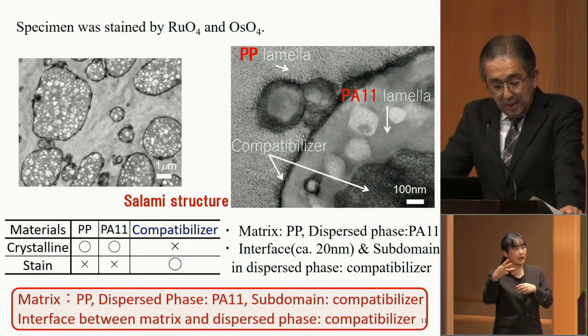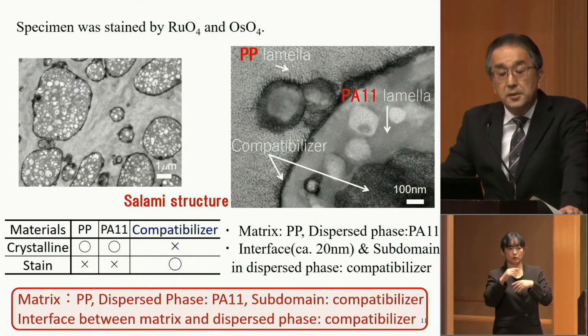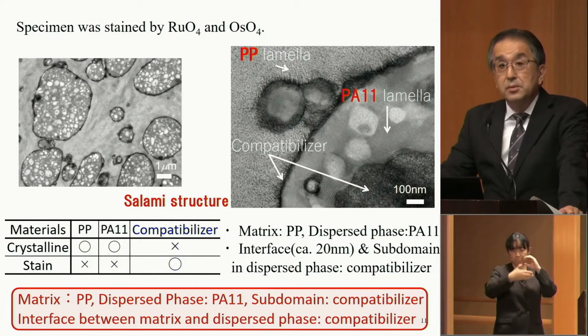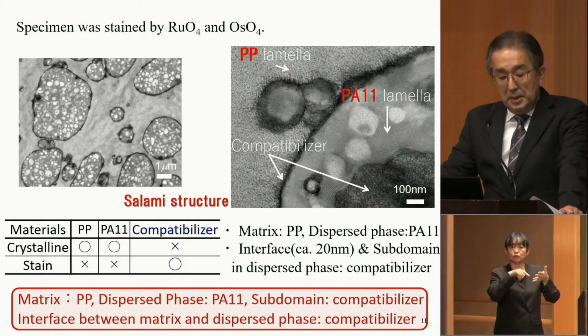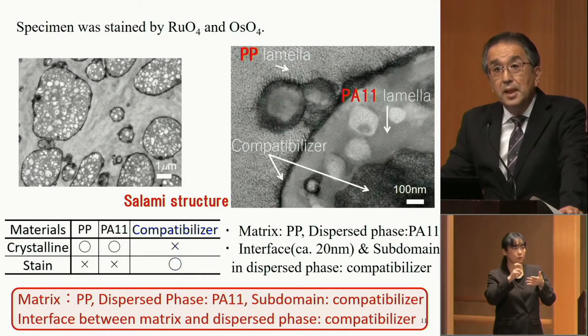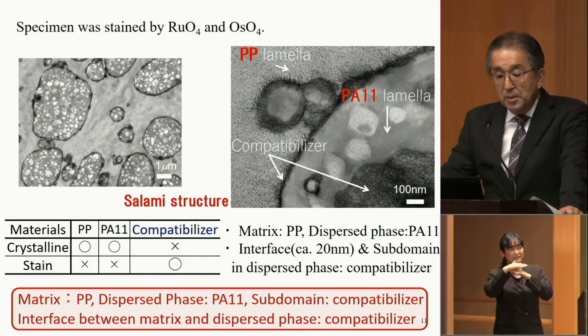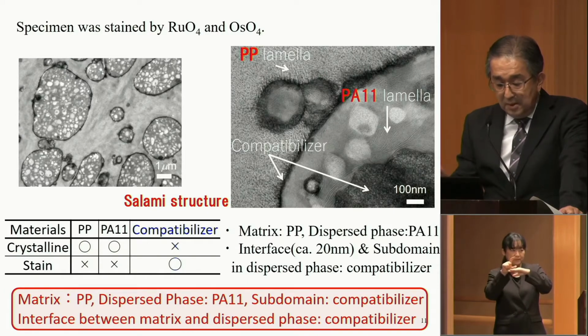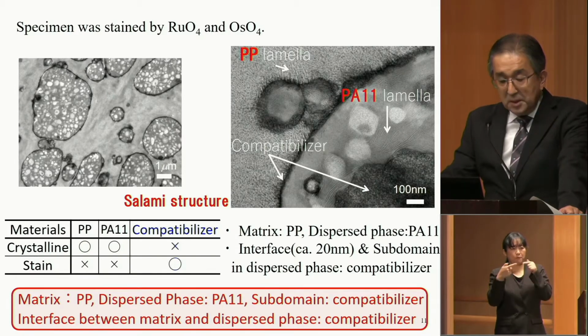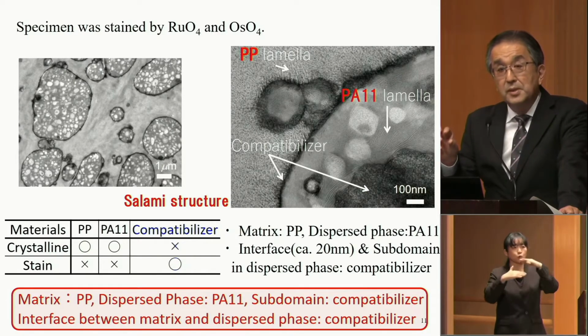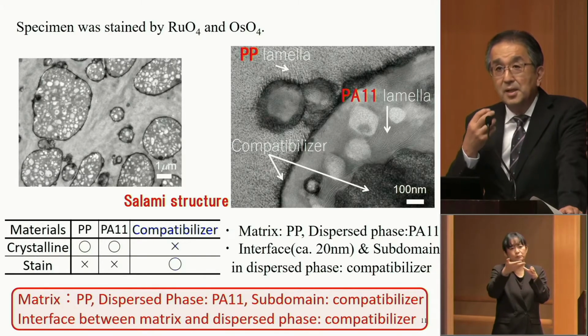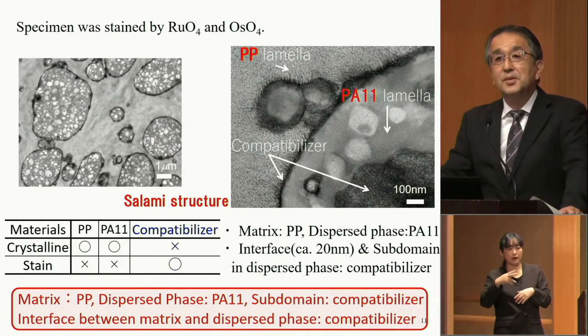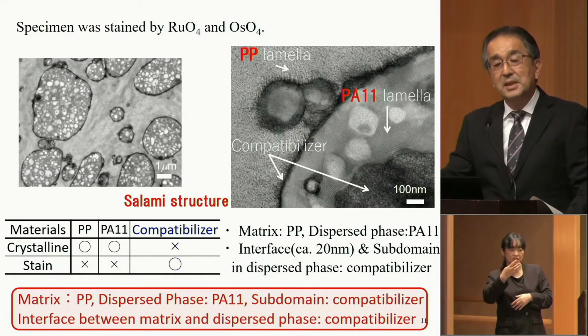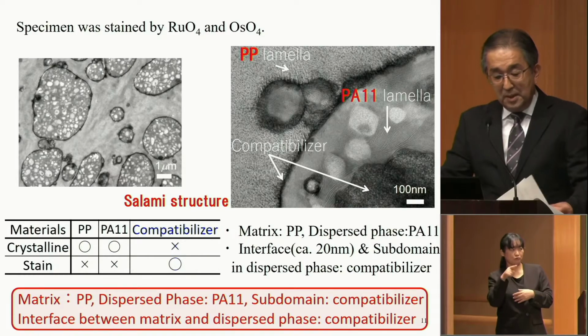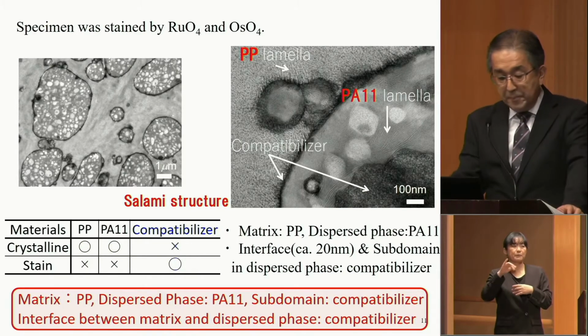This shows the high-order structure of the polypropylene/PA11 alloy. The matrix is polypropylene, and the islands are nylon 11. The interface is the compatibilizer to promote mixing. This is a new structure called the salami structure, for the island structure has a lake structure inside. So it has very good features. Let me explain that.